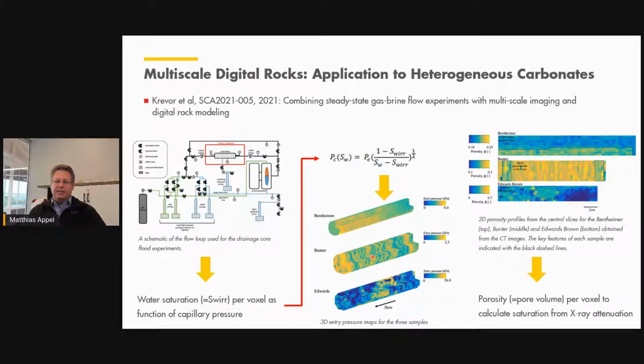And that is exactly the information that is needed to predict, for instance, the CO2 flooding through the porous structure. Because if the capillary pressure between the CO2 brine system exceeds the entry pressure into a certain pore, then one can assume that the CO2 will enter that pore. It's kind of a logical thing there. But that is a very neat indication, in my opinion, where the scanning at different length scales results in a workflow for digitally describing the pore scale dynamic processes.